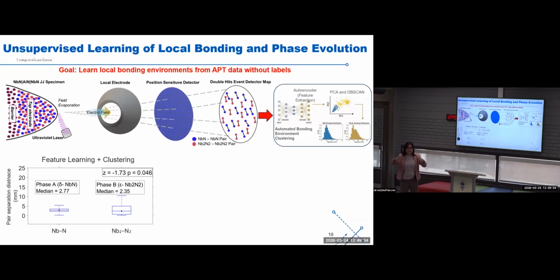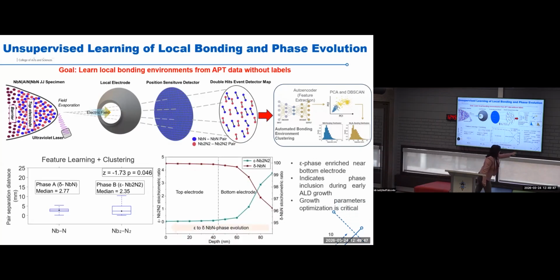Locally doesn't mean that it can be on the surface or the bulk, because we need to understand that, which is very important, because it is directly linked with the growth optimization, right? So we see this, then we try to map them. And when we map them, this is our substrate. So from substrate to surface, we see the epsilon phase, which is not desired, is high. As it grows further towards the surface, it is getting ideal, delta, like 2 phases are there, right? So epsilon phase is not desired, delta phase is desired. So it's closer to the substrate, but as the growth takes longer and goes forward, the desired phase is formed. So that means something is going on just in the beginning of the growth, right?